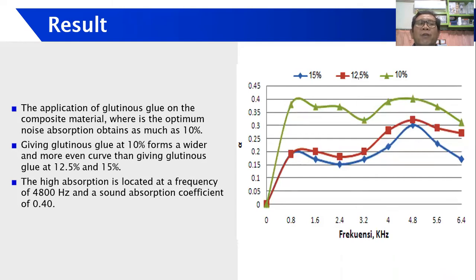For the application of glutinous glue on the composite material, the optimum noise absorption was obtained at 10%. Giving glutinous glue at 10% forms a wider and more even curve than giving glutinous glue at 12.5% and 15%. The highest absorption is at a frequency of 4,800 Hz with an absorption coefficient of 0.40.